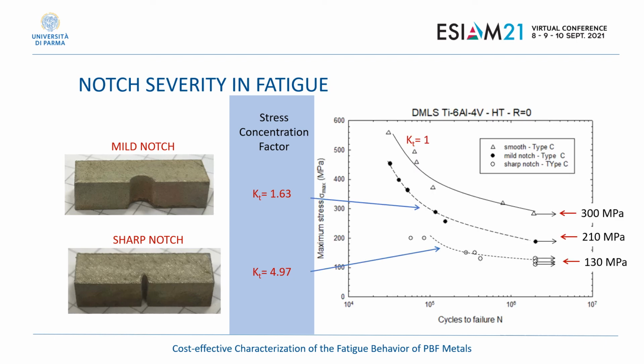We performed testing on those notched specimens and determined the data in this plot. We have the reference data for the smooth configuration, and for those we achieve a fatigue strength of about 300 megapascal at 2 million cycles. When we test the notched specimens, we determine different fatigue strengths at 2 million cycles. The difference is quite significant, and it's related, of course, to the level of stress concentration. We go to 210 megapascal for the mild notch effect, and down to 130 megapascal for the sharp notch specimen configuration.